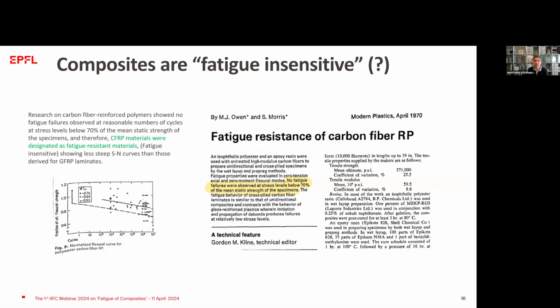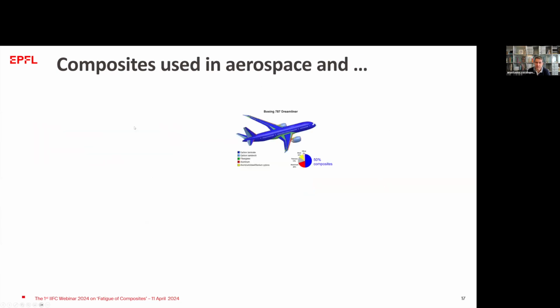It was the phenomenon where, while testing unidirectional composites along the fibers, no damage was identified, and then the material failed suddenly at a certain point of cycles, or at a certain point of stiffness degradation, without any announcement before. That's why it was called the sudden death phenomenon, and that's why they called composite materials fatigue insensitive. We'll see that this does not hold true anymore.